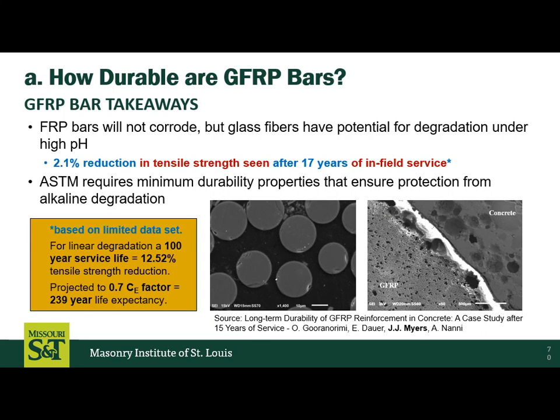The other thing, when we did the Texas project, we put witness bars in the deck, and the witness bars could be cut out and removed so that we could do tensile testing on the bars. And if you look at this here, we saw after 17 years, 2.1% reduction in the tensile capacity. Now, we didn't have lots and lots of tests, and we don't have data at this point over lots and lots of years, but the framework of what we did in this study was supposed to set it up for us to collect more and more data.